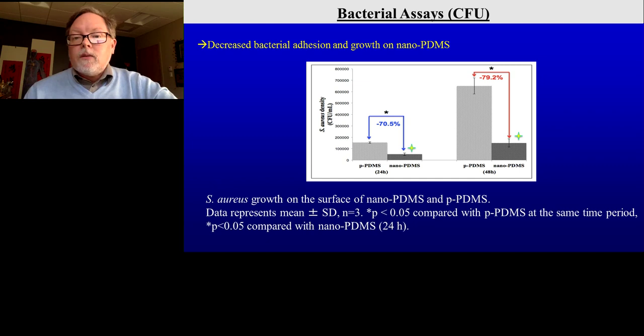Bacteria results showed exactly what we expected. So here is for Staphylococcus aureus, a bacteria that commonly infects catheters. In fact, you might be aware of MRSA, which is the antibiotic-resistant version of this bacteria. And you can see after 24 hours, 48 hours, the density of bacteria, or the colony-forming units per ml, significantly lower when we simply put nanoscale features on those implants. Nanoscale features resembling those that are on the insect wing that I presented in the beginning.